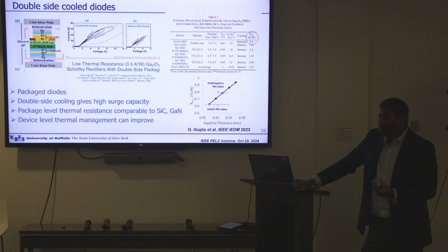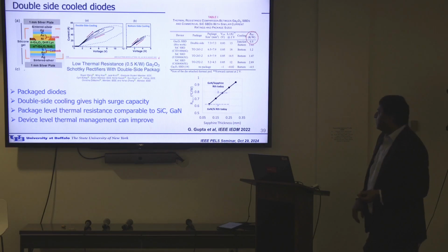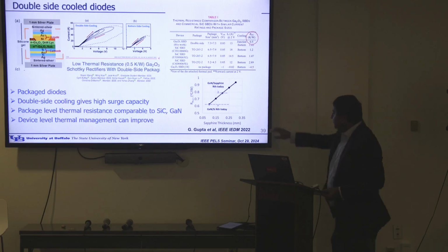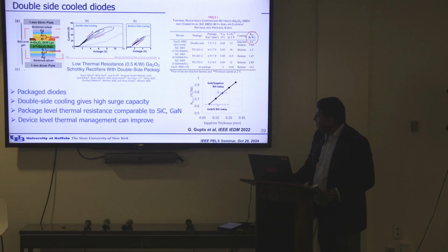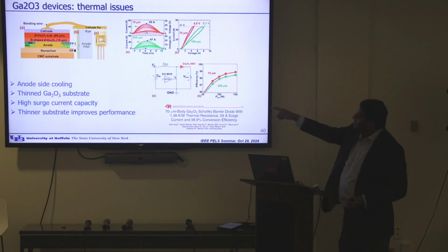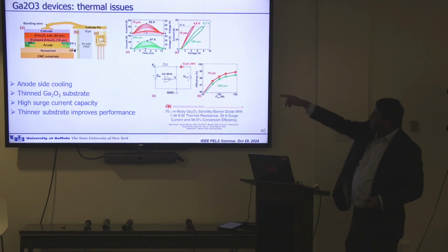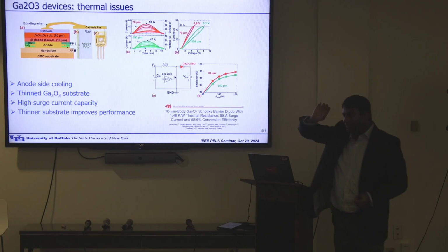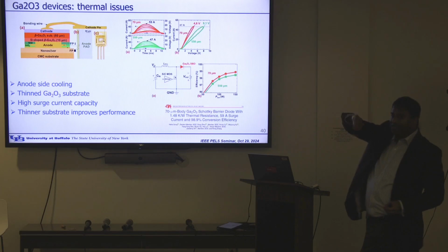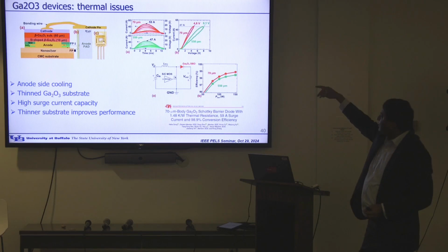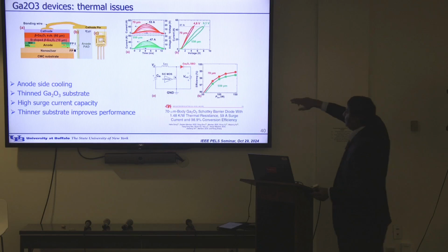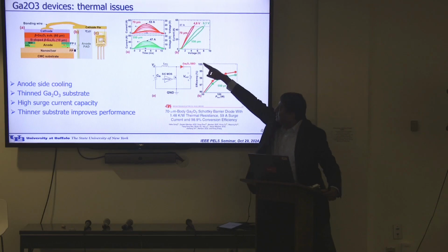I think what works in the favor is, if you go to larger currents, you have larger areas, and the area gives you low resistance, right? I would say enough work has been published that it's not failing thermally. Another work, this is from China, did single-side cooling. They thinned down the wafer and did top-side cooling. And you can see these devices can have high surge capacity, right?